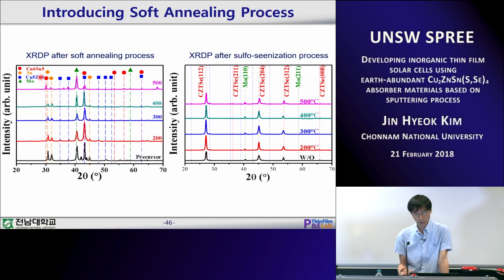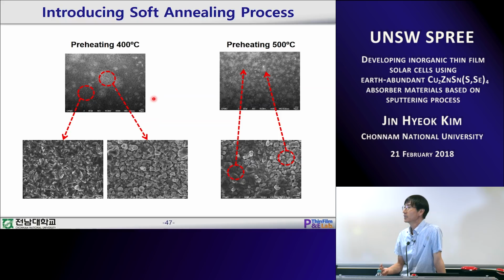So we could form alloy, and after this pre-annealing process, we form a CZTS thin film absorber layer without a big secondary phase based on this X-ray result. But there are many secondary phases in reality. There are 2 issues. If we pre-anneal the sample at high temperature, like 400 and 500, we see a nonuniform surface morphology. This is pre-annealed at 400. You see the big change in microstructure from one area to the other. And at 500, the difference becomes worse.